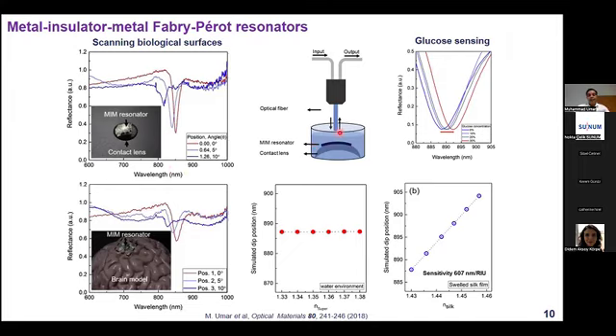And then we used this device, conformed onto the contact lens, to measure glucose concentration in a water solution. When we put the sample in the glucose solution, when there was no glucose you can see the resonance peak, and when the concentration of glucose in the water was increasing, the resonance was shifting to a higher wavelength. So this means this could be used to sense glucose concentration.